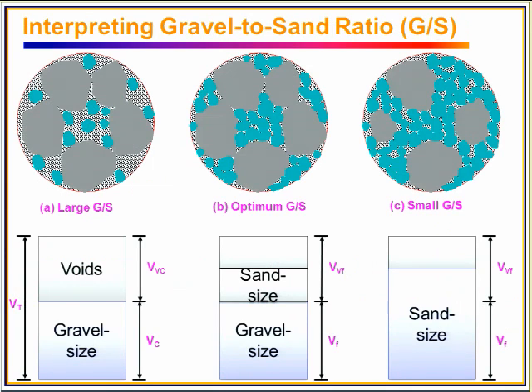Before I move on to the validation stage, I just want to give a quick explanation about this parameter. Basically, we consider the mixture as gravel size and sand size based on the USCS specification. Gravel size means passing 75 millimeter and retained on the number 4 sieve. Sand size means passing number 4 and retained on 75 micrometer. If we have a large GS ratio, that means gravel size dominates in the mixture, and the sand size just fills voids between the gravel size particles. So there should be some optimum range for each specific gradation.